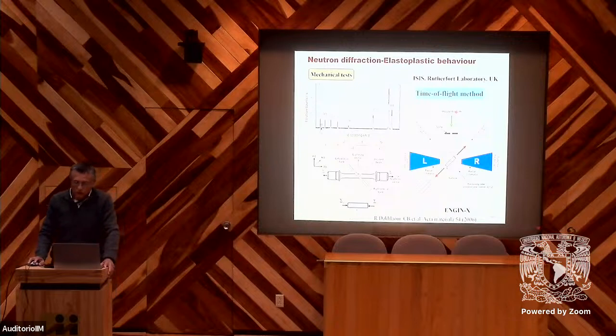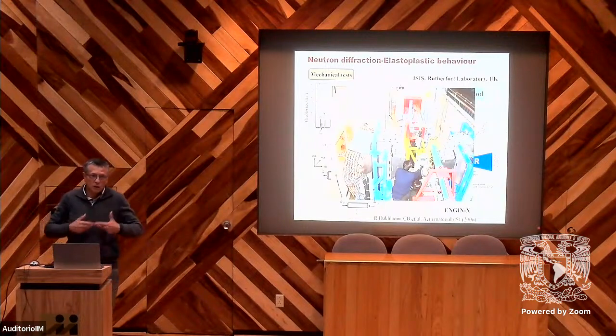For this, we have a source and two fixed detectors, the left one and the right one. You can see the photo here. This is the source, and we have the two detectors, the left one and the right one. In the middle, we can put big machines to make tensile tests or compression tests. These are some results of testing by tensile test or compression. This is the result for the austenite, and this is for the ferrite.